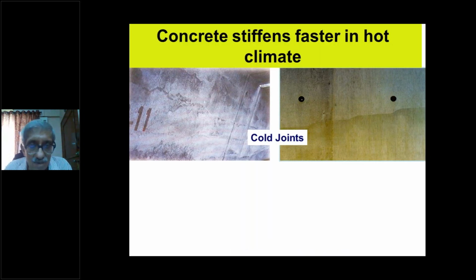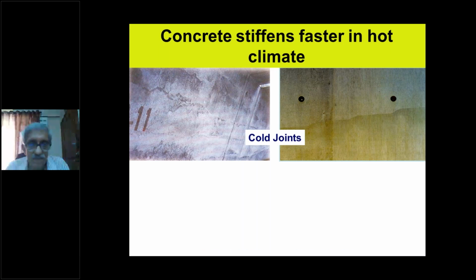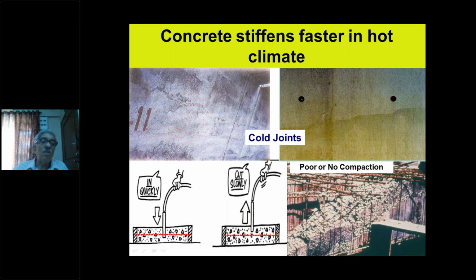Talking about the cold joints, which I told you, here you can see a sketch where the operator is lowering the needle right past the fresh layer and it goes slightly into the lower layer. So you have to be sure that the lower layer is not set hard. Otherwise, you will get a cold joint like this. You can see here.